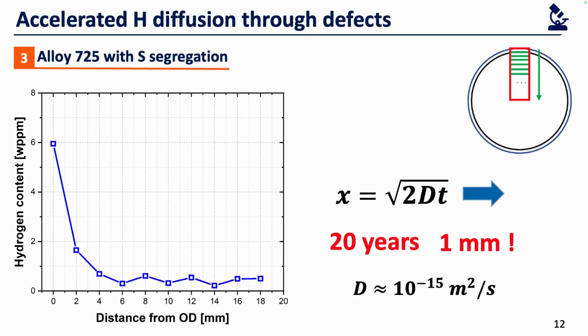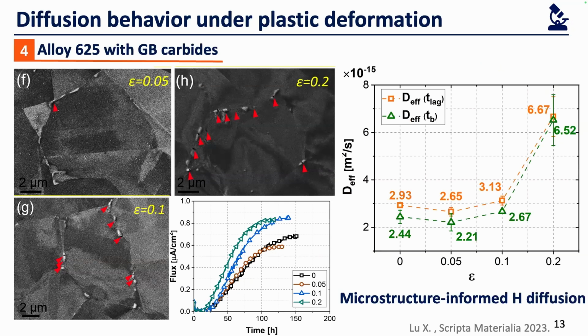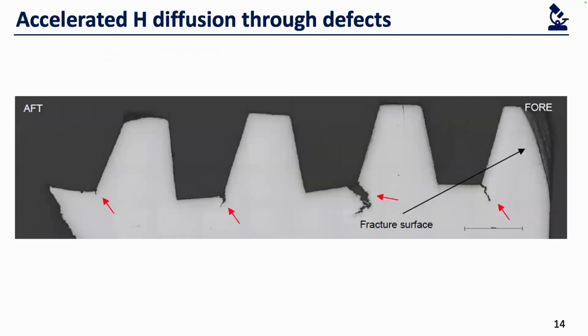Something must happen, right? So then we did a permeation test with the samples being loaded higher than the yield strength, which means we load the samples to the plastic deformation condition, and then we study the permeation behavior of the nickel alloy. This is alloy 625. It has some grain boundary carbides alongside, and we saw that when we increase the strain, we observed the cracking of those carbides, and definitely, besides the cracking of carbides, there should be something happening also along the other grain boundaries, such as the vacancy formation that other researchers proposed. And what we see is that the permeation or the diffusivity of the hydrogen when we strain the material is largely increased. So this may indicate why we have such a high hydrogen diffusion depth.